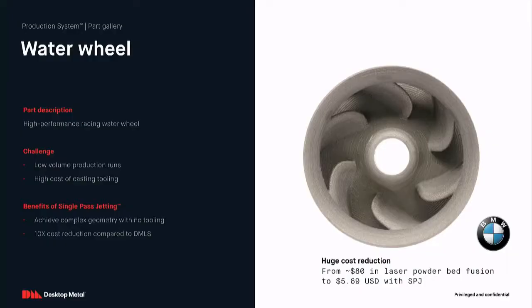If you compare it, for example, to other binder jetting systems like the HP Metal Jet, our inherent speed is about 4 times faster with a build envelope that's much larger, giving you much better productivity per day. And then we have some advantages to the way that our process works in that we have the ability to inert our system, so we can work with reactive metals. We have solvent recovery. Our process uses piezo heads, so that gives us the ability to work with solvents, which means we can work with low alloy steels. We can work with reactive materials. In the world of thermal inkjet, which is what HP uses, you can only work with water. And if you work with water, it's going to be very difficult to do low alloy steels reliably. It's going to be very difficult to do reactive materials. And so those are some of the differentiating features.